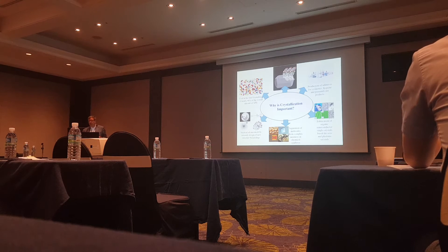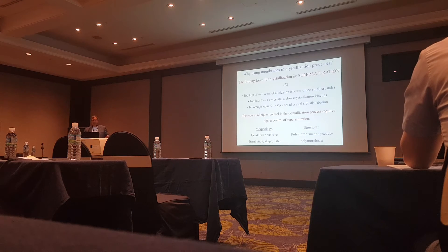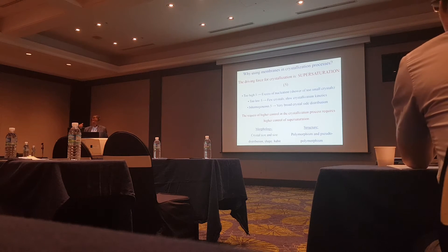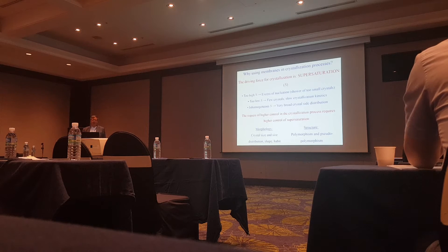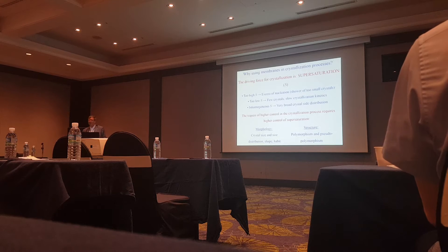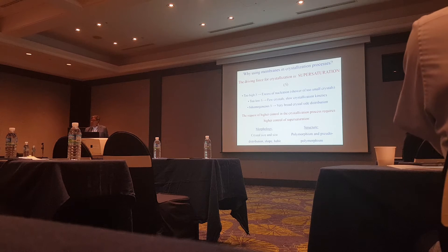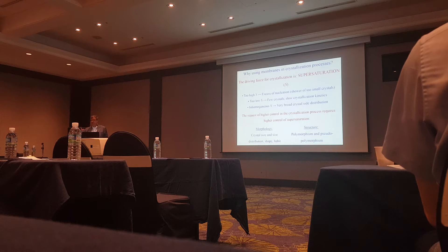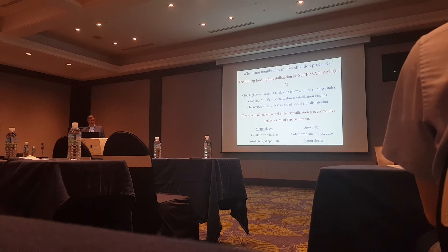When you concentrate twice in reverse osmosis, if you don't change the pressure, flux goes to zero — and that does not happen in membrane distillation. In membrane distillation, we can not only separate salt from water, but we can concentrate and concentrate the brine to the point that we induce a supersaturated solution on the brine side. That means we can induce heterogeneous nucleation, which is the controlling step for crystallization — and crystallization is the most interesting operation for separation, purification, and concentration of minerals.